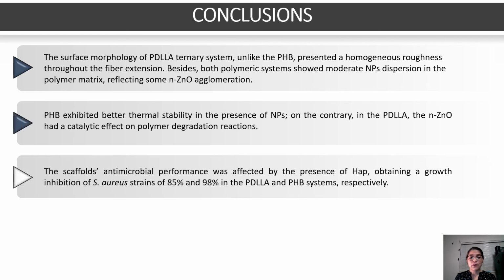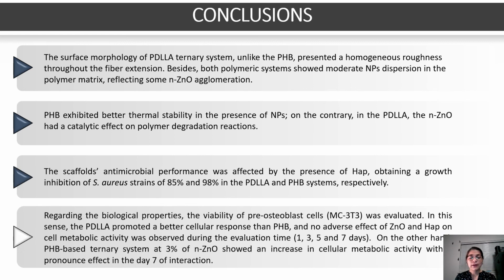The scaffold antimicrobial performance was affected by the presence of hydroxyapatite, obtaining a growth inhibition of S. aureus strains of 85% and 98% in PDLLA and PHB systems respectively. And regarding the biological properties, the PDLLA promotes a better cellular response than PHB.